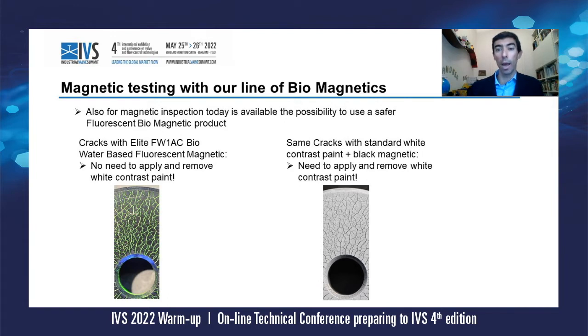You see the cracks are shown very well, but you need the two products, the white background paint and the black magnetic. And at the end of the inspection, usually you need also to remove the white contrast paint, so you need a solvent. So that's 3 products and a lot of time. On the left-hand side, whereas if you use the Elite FW1 AC bio water-based fluorescent and dual magnetic, there is no need to apply and remove the contrast paint, and the cracks, as you can see, are shown very clearly in the same way or better compared to the picture on the right, which is the same piece in the same position. So you can really compare the indication.